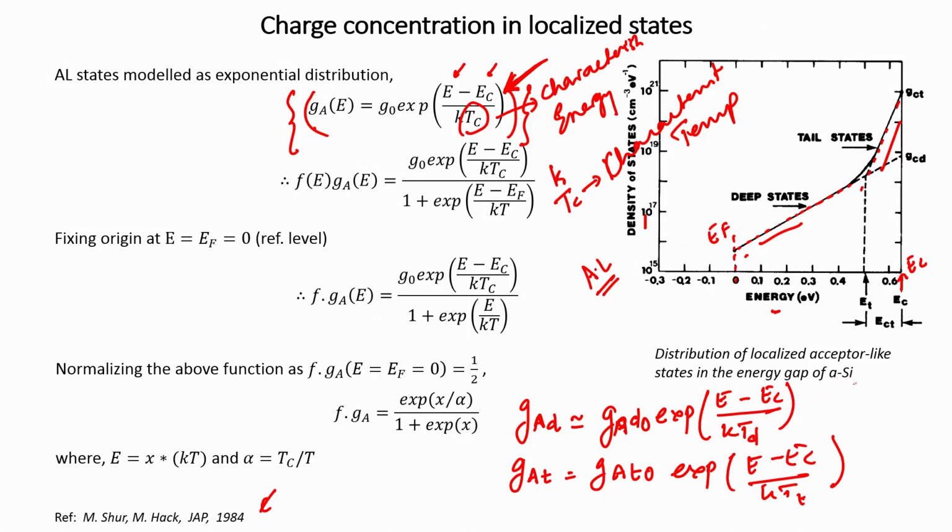So this is the first step towards any modeling, which is to define the density of states, and we can define this using an exponential definition with something called a fitting parameter, the characteristic temperature.